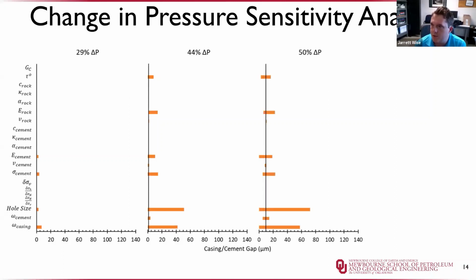So same thing with reducing the pressure down to 50%. We see that the base case has a microannuli size about 10 microns, but now the parameters are starting to change it more, where if you have a smaller hole size, you can actually reduce the microannuli size. But if you have a bigger hole size, you're getting up to almost 80 microns.